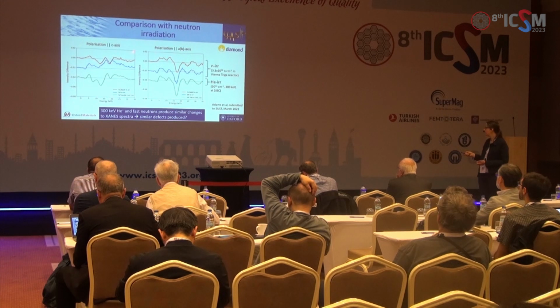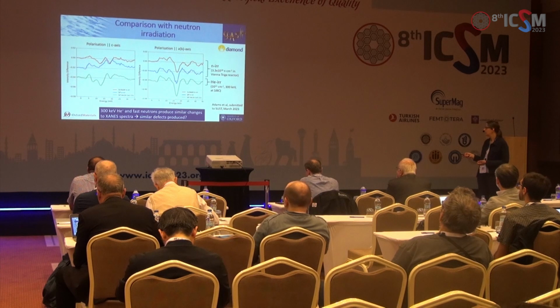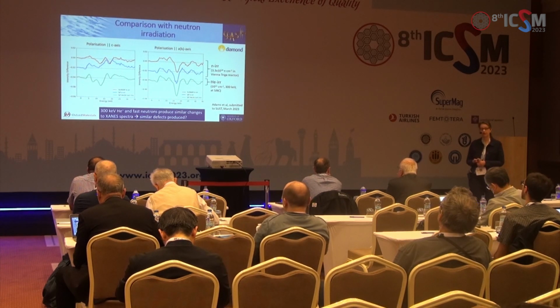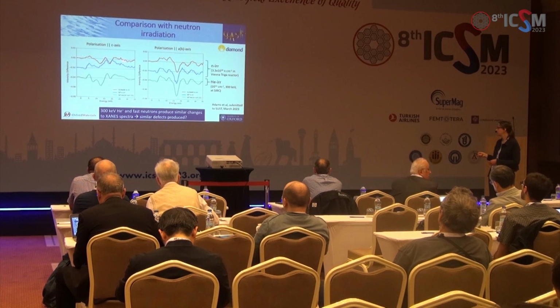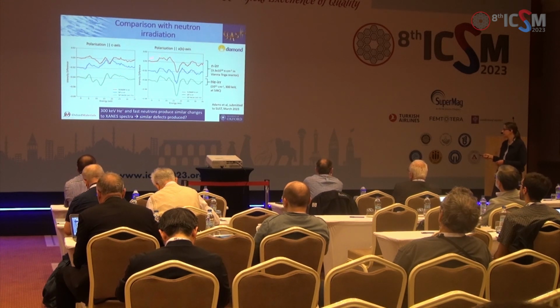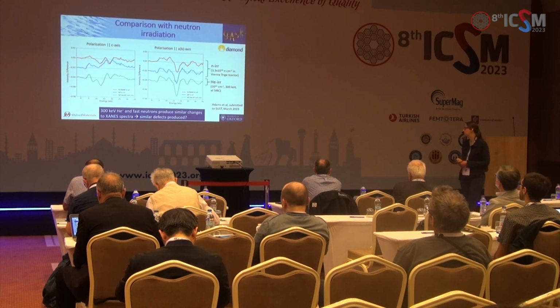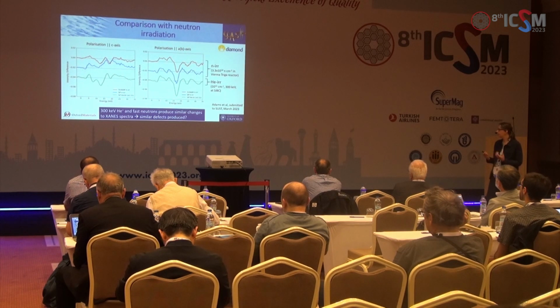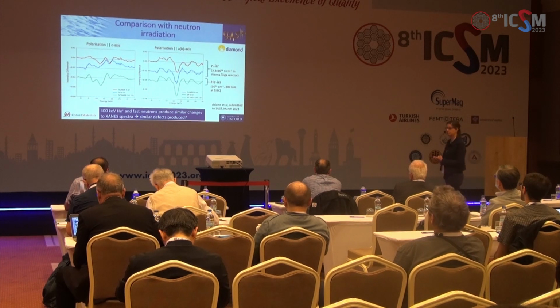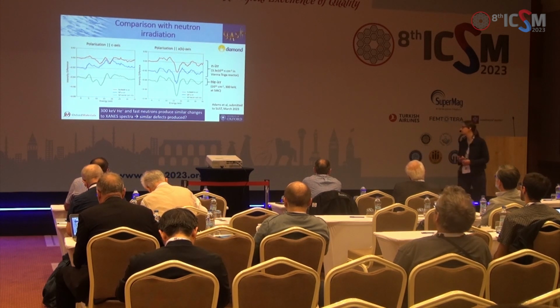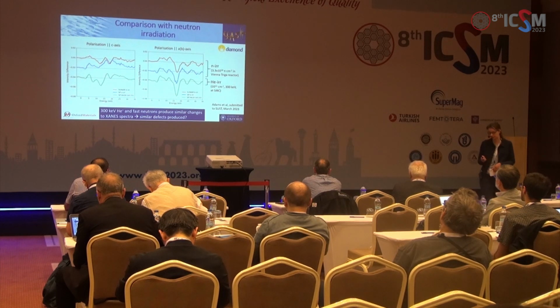On the bottom here is our iron irradiated, just like I showed before, the different spectra. And we've looked at some of the samples that Vienna irradiated. Two samples, one is a Sunam sample and one's a superpower sample. And if you look at the shape of the different spectra, it's really very similar. It's very striking in this orientation that the changes are very similar with neutron irradiation compared to helium irradiation. So it wouldn't be crazy to think that we might be producing the same kinds of point defects in the neutron irradiation compared to the helium ion irradiation, based on these very similar spectral changes that we see.